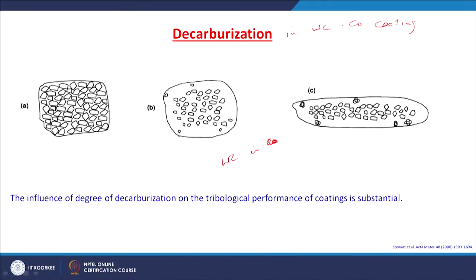The tungsten carbide cuboids are set in a cobalt binder. At high temperatures during coating, the tungsten carbide dissolves, and upon impacting it becomes a lens-shaped splat. They coalesce with each other forming flat lens-shaped coatings on the substrate. Decarburization must be controlled to improve tribological performance, and we will examine case studies with different oxygen-to-fuel ratios.